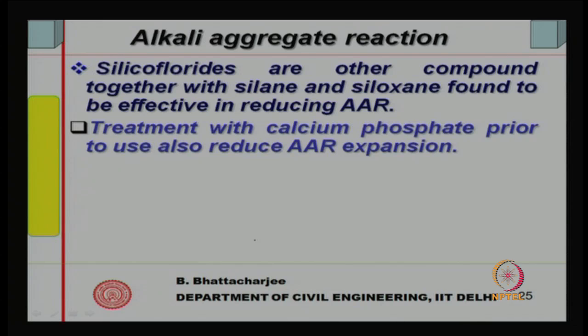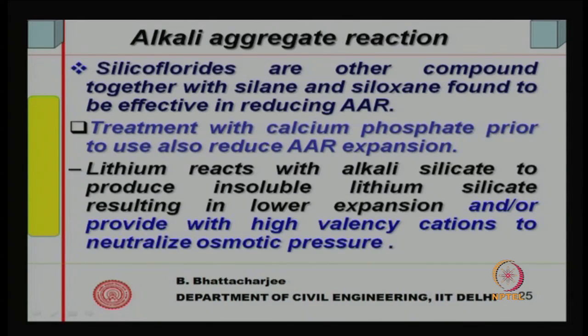In fact, silane and siloxanes are used in water repelling systems as well, waterproofing systems as well. We might look into this sometime in connection with surface coating and durability of concrete. But silicofluorides together with silanes and siloxanes are also found to be effective in reducing alkali aggregate reaction. Calcium phosphate, if you use it with the aggregate prior to their use, also reduces the alkali aggregate reaction expansion.